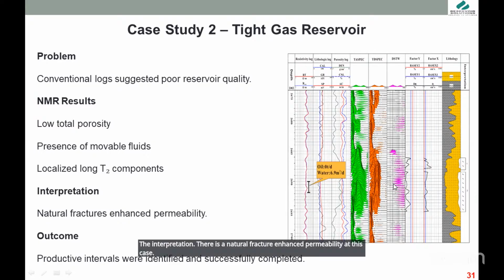And by the way, we mentioned that we have only one case for sandstone to have a secondary porosity. Sandstone is always primary porosity. The only case where you find secondary porosity or fracture in sandstone is the compacted sand and the tight sand. In this case, the fracture will occur afterwards because the primary porosity will decrease due to the compaction and due to the presence of the fracture. It is the only case where you can find sandstone with secondary porosity. But you cannot detect it, of course, with the conventional logs.